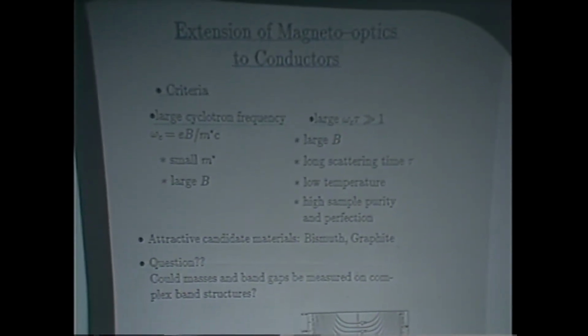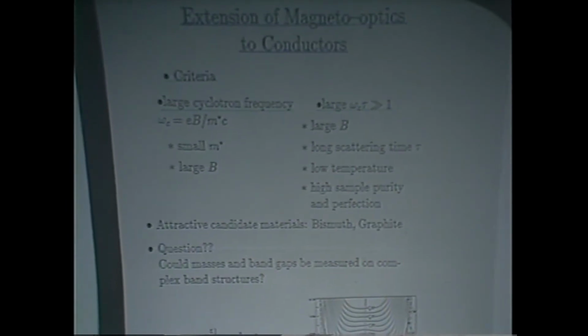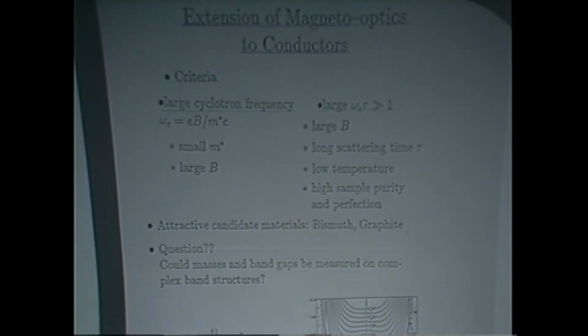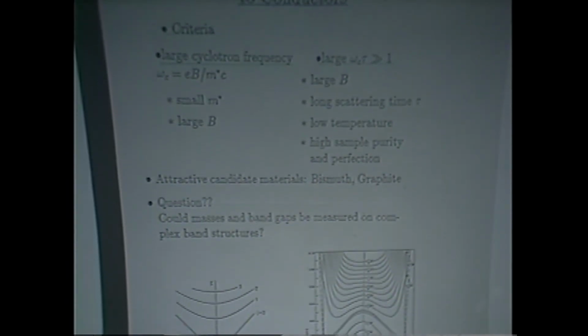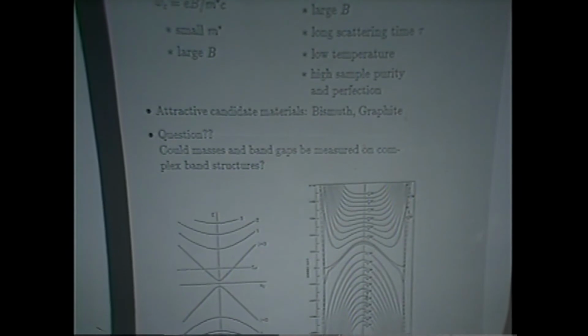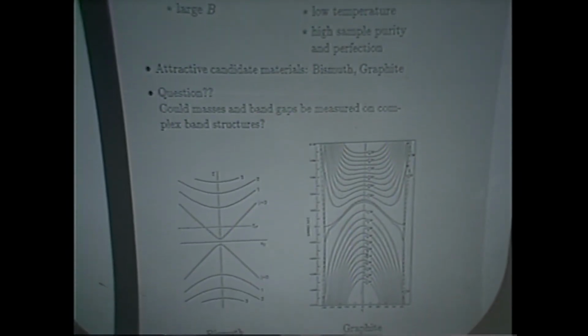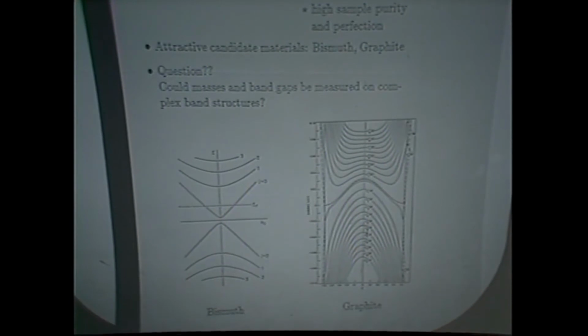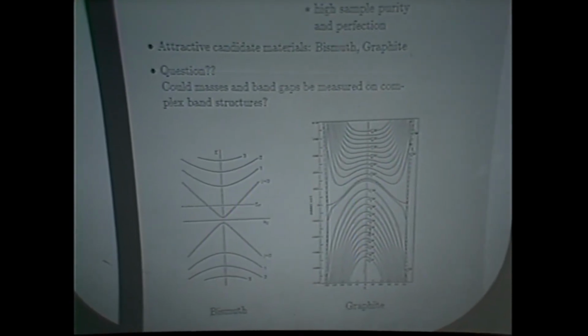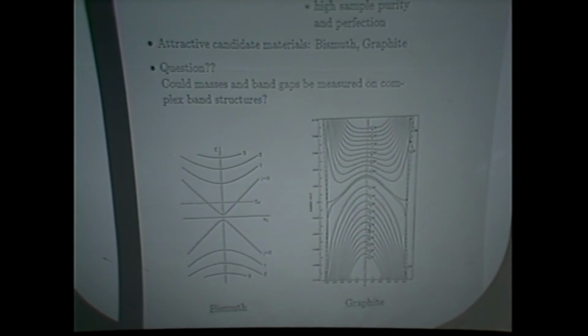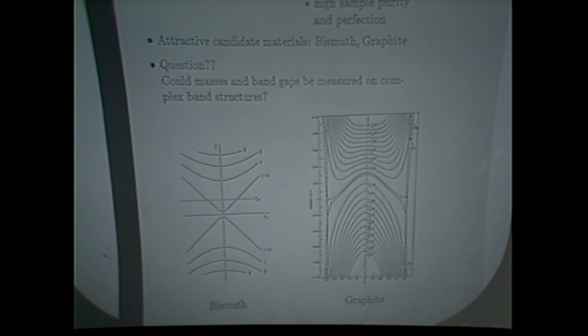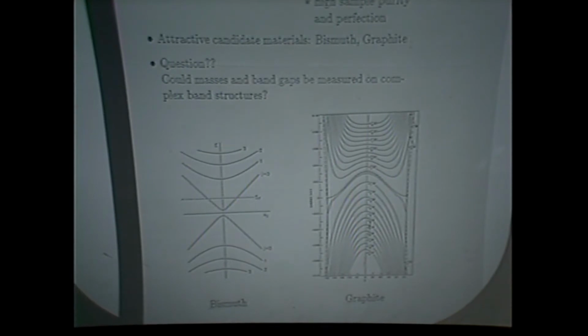Now, at the Lincoln Laboratory itself, in those days, we were limited to about 40 kilogauss, which wasn't much by today's standards. And that meant pretty much that we had to work with materials with small masses. There were two candidates of this type, bismuth and graphite. I knew something about bismuth because I came out of the University of Chicago, which had a long history of bismuth. And everybody in my lab, I was working on superconductivity, but everybody else was working on bismuth. So I couldn't help but know something about bismuth, and that was a big plus for me. And Jean knew something about graphite. So between the two of us, we had a pretty good background to enter into this field.